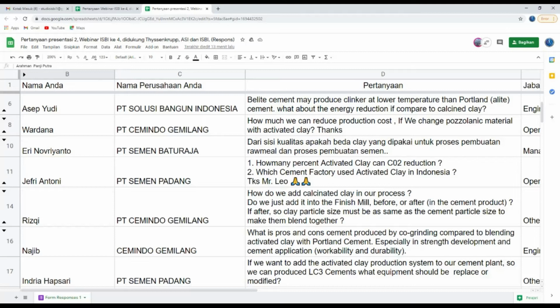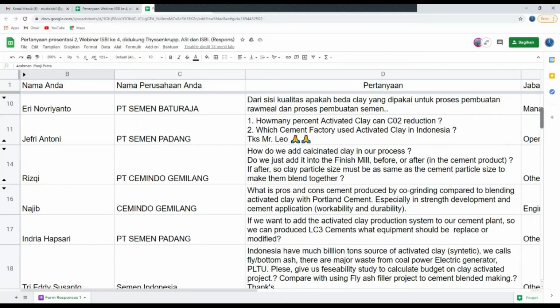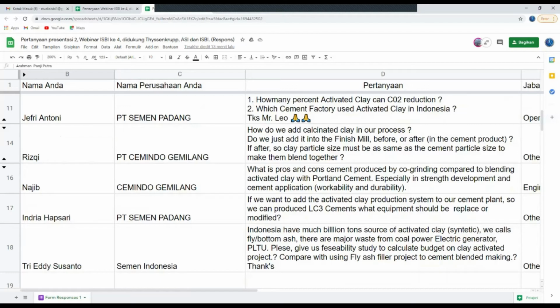So the next one. This is something I just tried to answer in the question before. The question is the pros and cons of co-grinding and separate grinding, especially strength development, workability, durability. What we can say here is that activated clay is quite a fine material. You easily reach Blaine values of 5,000, 6,000, 7,000, 8,000, which is a very high surface and leads to a high water demand.